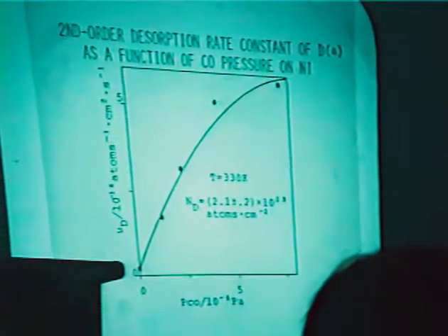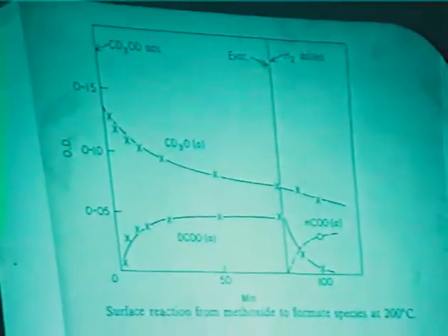So, by extending such behavior, we study the influence. Then, to make a long story short, we study, for instance, methanol decomposition. And we found that the first species observed was methoxide, then it goes through to formate ion, and formate ion decomposes.